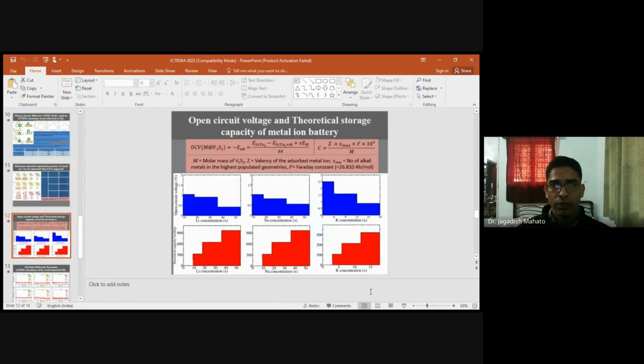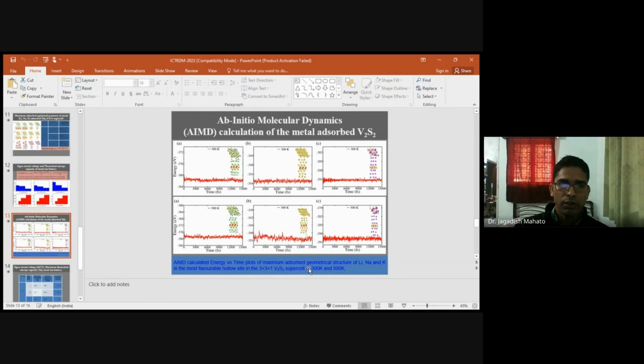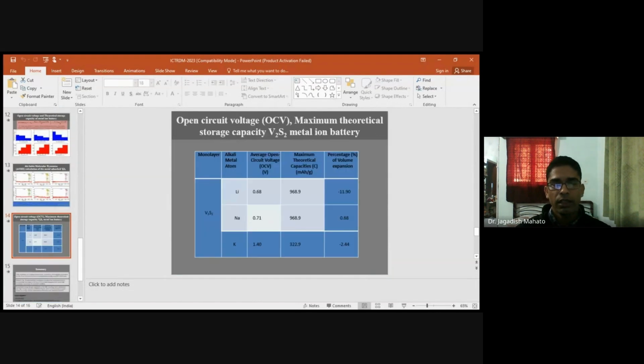After calculating those adsorption energies, we calculate the OCV using this formula, and the maximum or storage capacity using this formula. Using this, we have plotted the open circuit voltage against the lithium or metal atom concentration. Then after getting the maximum adsorption, we check the thermal stability of that structure using AIMD calculation, and we found that the structure is stable at both 300 and 500 Kelvin. Here we tabulated the average OCV for the lithium, sodium, and potassium adsorbed V2S2 monolayer, and we see that the average open circuit voltage for lithiated V2S2 is 0.68. For sodium it is 0.71, and for potassium it is 1.4 electron volt.